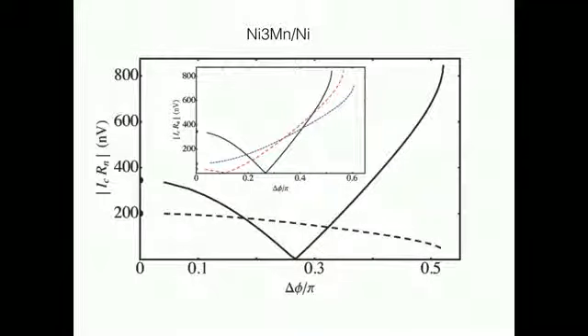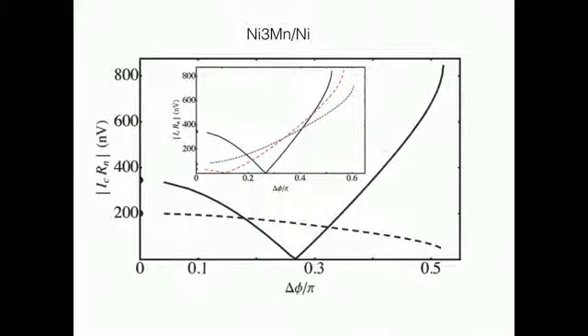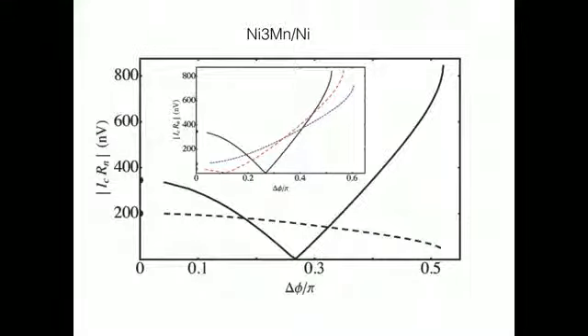We are drawn to the curious consequence of this, a zero-pi transition shown as a V-shaped solid line. The system is too wide for the Buzdin-Bulaevskii-type transition measured in homogeneous films to appear here.